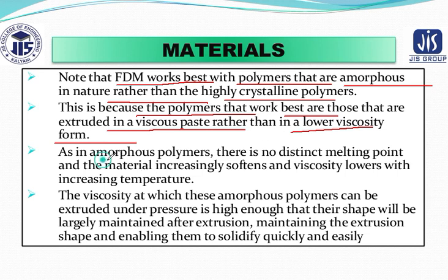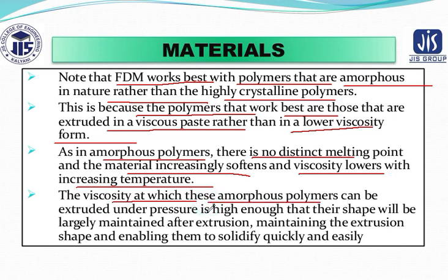Now, as an amorphous polymer, there is no distinct melting point, and the material increasingly softens and its viscosity lowers with increasing temperature. The viscosity at which these amorphous polymers can be extruded under pressure is high enough that their shape will be largely maintained after extrusion, enabling them to solidify quickly and very easily.